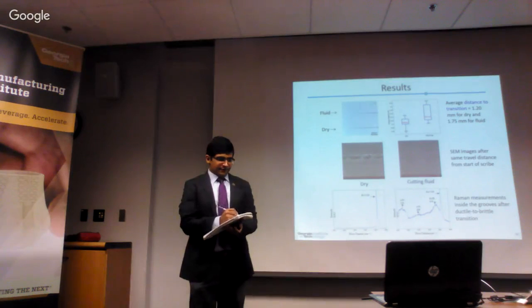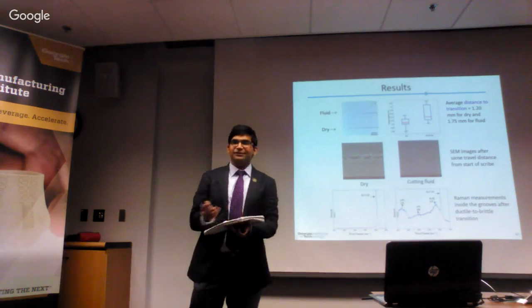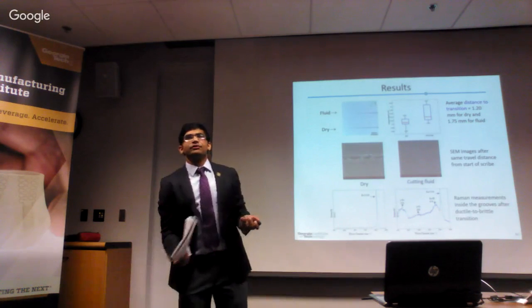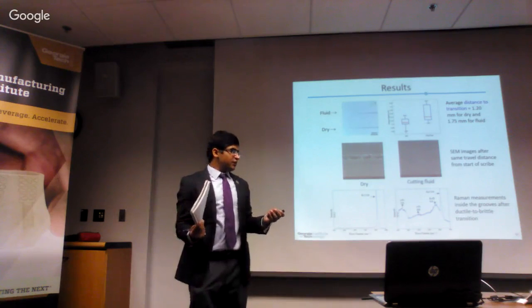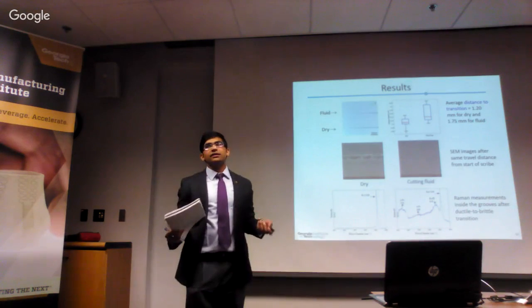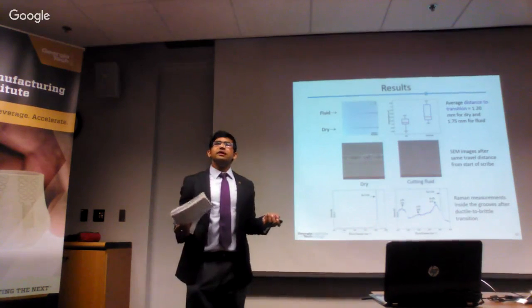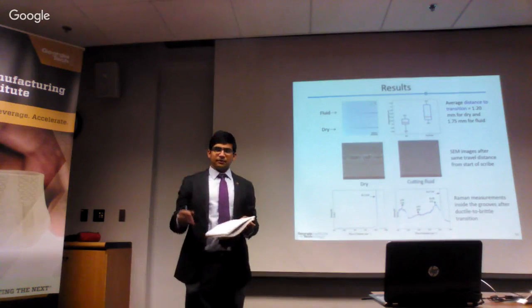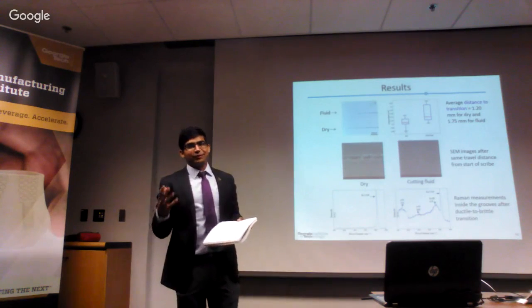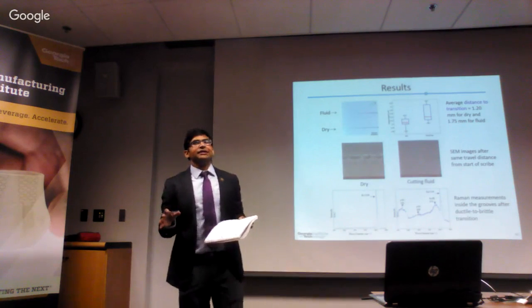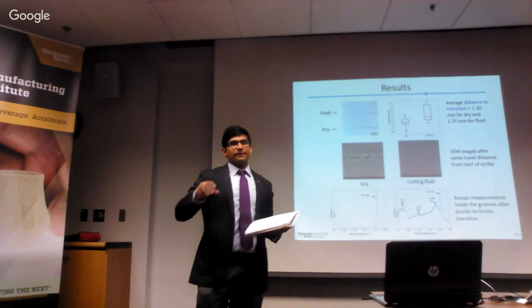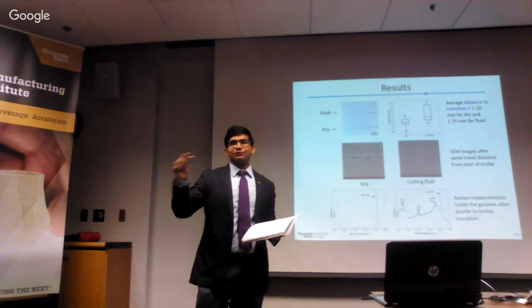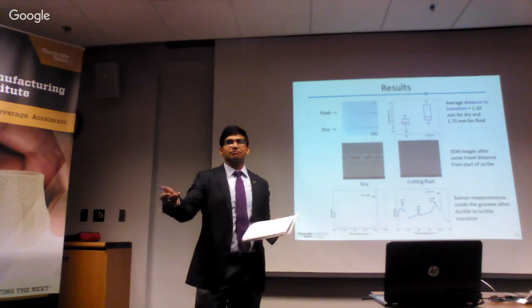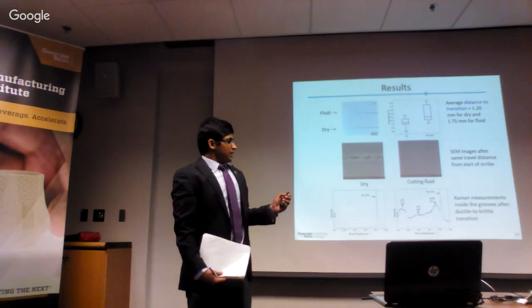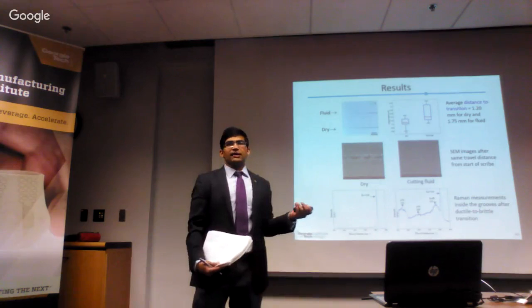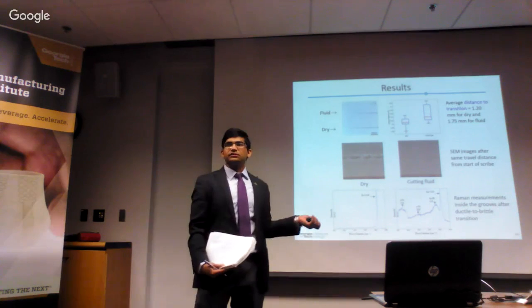About friction, that is the first thing which comes to mind while using cutting fluid, because it's known to reduce friction in machining operations. We found that the friction coefficient does not change significantly, because this cutting fluid is a water-based cutting fluid with proprietary chemicals, mostly sodium and potassium hydroxide or some salts of it. They sent me a concentrate which I measured at 97 ml to 3 ml, so it's mostly water with some ions like sodium and potassium. The friction coefficient did not change much between using the cutting fluid and dry conditions.